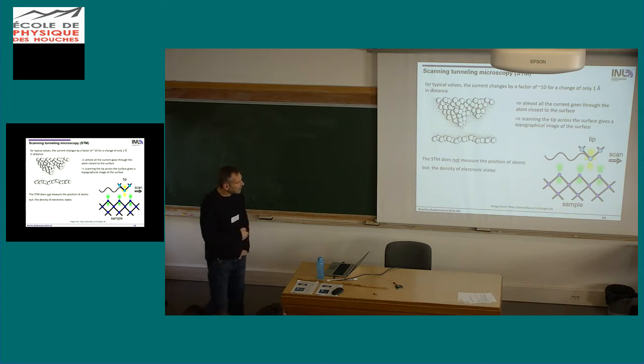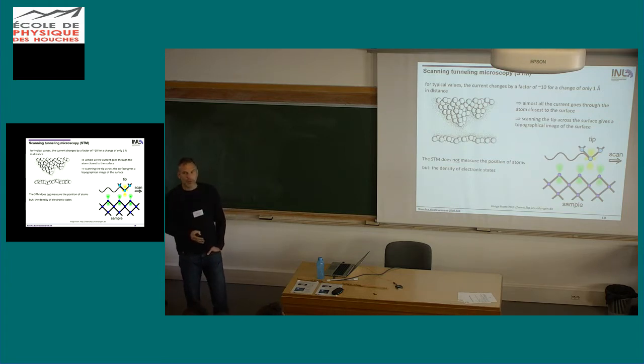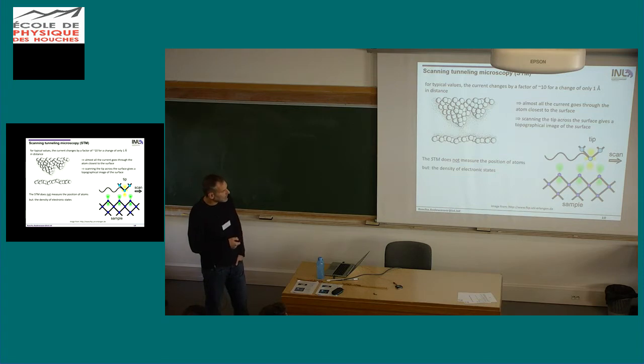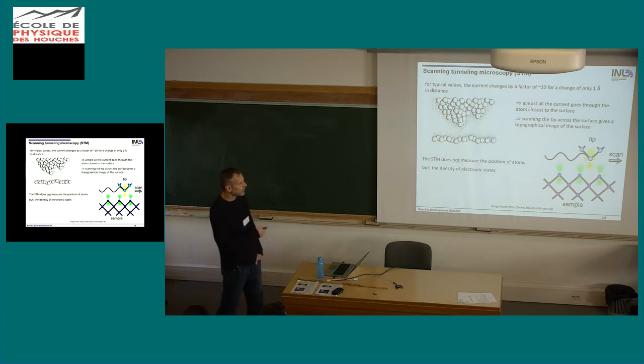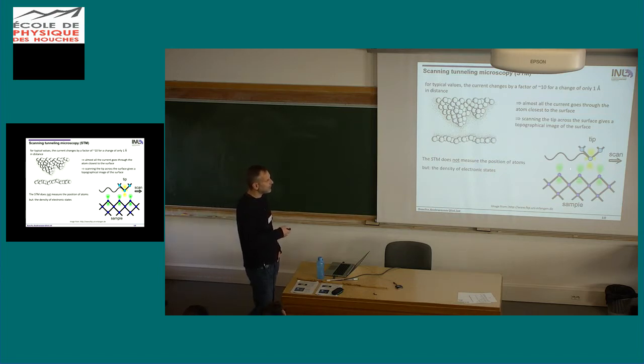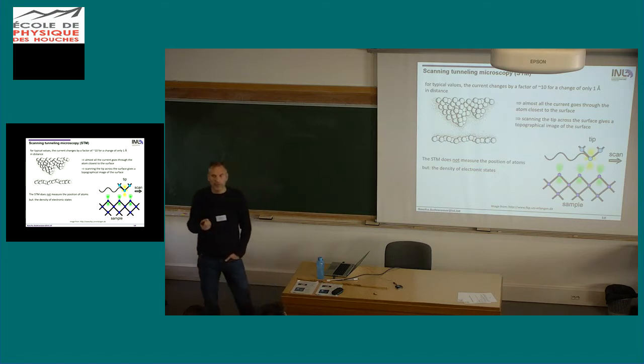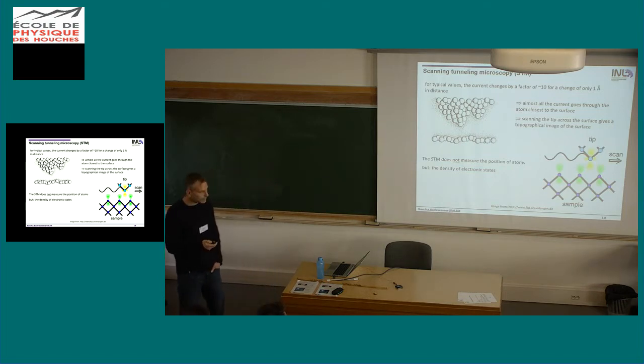On the other hand, normally people say easily, oh, we measure the surface topography or surface morphology. But this is not completely true because actually we are measuring currents. So the currents have to go, of course, into some electronic states. So we're actually measuring a surface morphology or topography of the density of electronic states. And this is in some cases very important because, for example, here we have a density of states corresponding to the atoms, but you can imagine surface structures where some of these electron lobes would not stick out of the surface, and then those atoms would, of course, not be as visible.